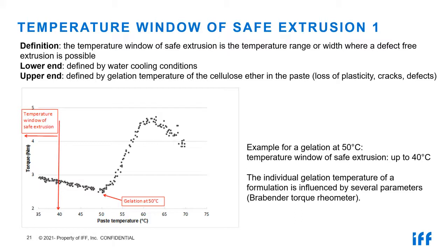And that's the reason why we have made a lot of work on this topic to enable you a safe extrusion. Especially for your plant, it is of importance because you do not have such a nice temperature control in your plant like in the lab, at least in most cases. Yeah, we defined a so-called temperature window of safe extrusion, where you can safely run your extrusion process also under plant conditions. And we defined this safe window to be 10 degrees below the gelation temperature. Where the gelation temperature is, you can measure with this torque rheometer trial. Here in this case, this is just an example.